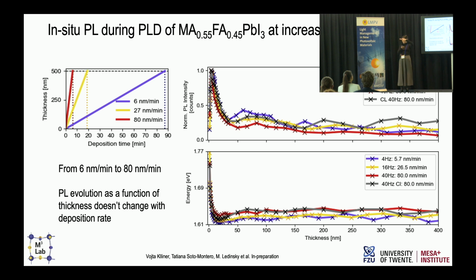So is this something you could control to efficiently transfer everything to the substrate, you think? Yeah, so the way we control it here is with the laser fluence, basically. We also need to decide what kind of fluence we use and also the spot size. That's another thing we have to decide, because the spot size determines how much the laser is ablating from the target.